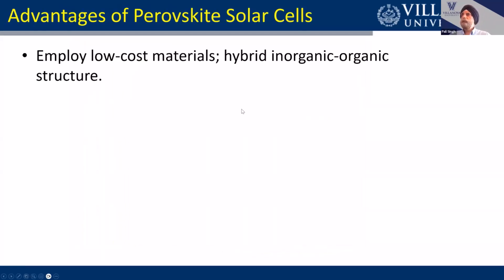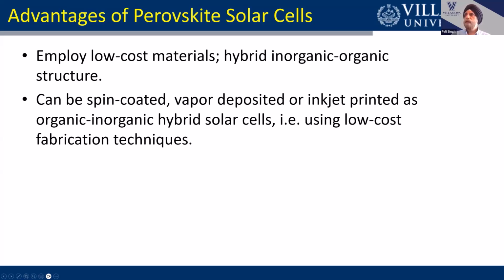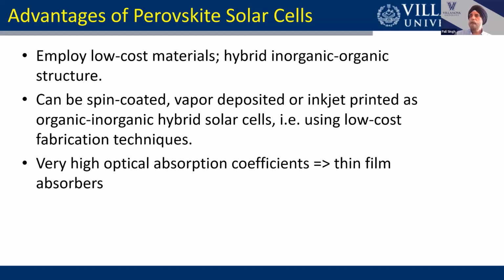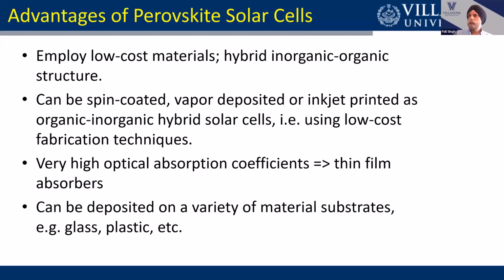So the advantages of perovskite solar cells is that they employ low-cost materials. They're a hybrid inorganic-organic structure, and they can be made by various low-cost fabrication techniques. So you can put the material on, spin coat it, and that's one way to deposit. You can use vapor deposition in a chamber. You can use inkjet printing. So there are various low-cost techniques for making these types of solar cells. And they have very high optical absorption coefficients. What that means is that you need very thin layers to absorb the light that's being directed onto the solar cell. And so that reduces the amount of material you need and the material costs.